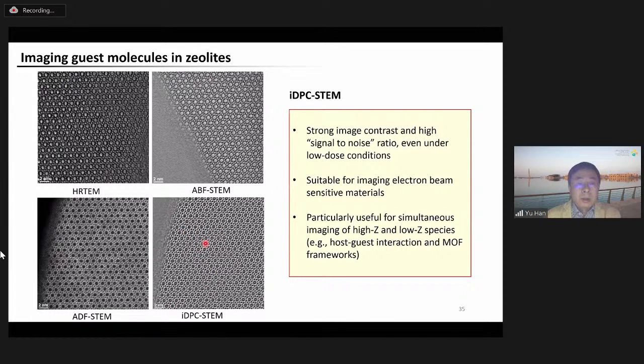And this organic compound contrast cannot be observed in other imaging modes. So this is a very unique property of iDPC-STEM. It's sensitive to both heavy elements and light elements. So iDPC is a promising low-dose technique and is suitable for beam-sensitive materials, and particularly useful for simultaneously imaging